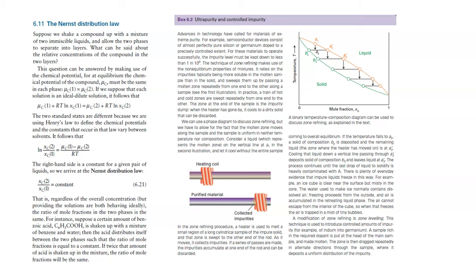A modification of zone refining is zone leveling. This technique is used to introduce controlled amounts of impurity, for example, of indium into germanium. A sample rich in the required dopant is put at the head of the main sample and made molten. The zone is then dragged repeatedly in alternate directions through the sample, where it deposits a uniform distribution of the impurity.